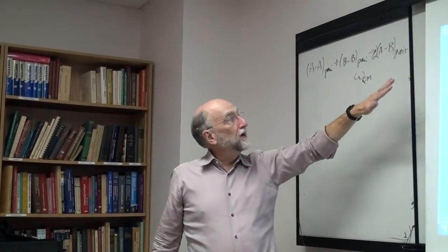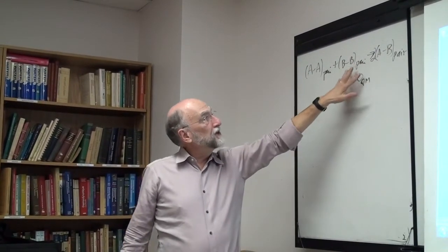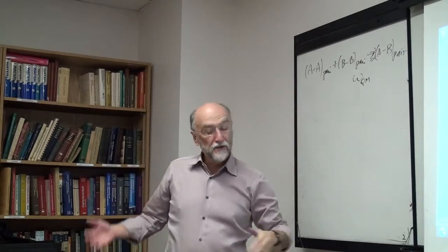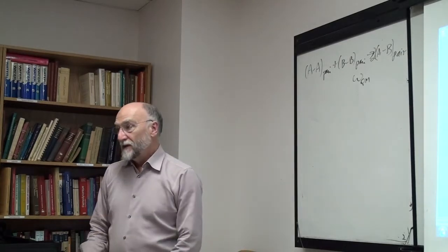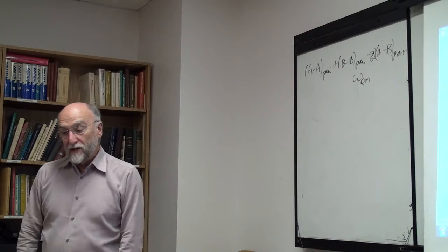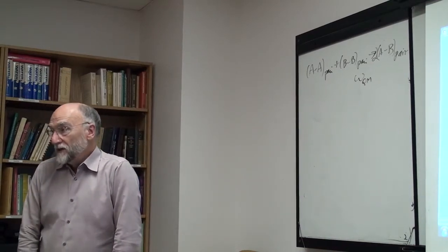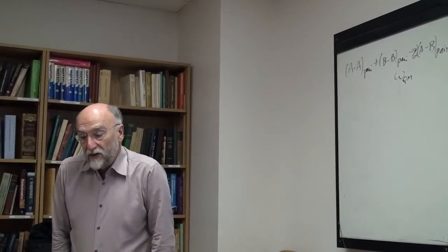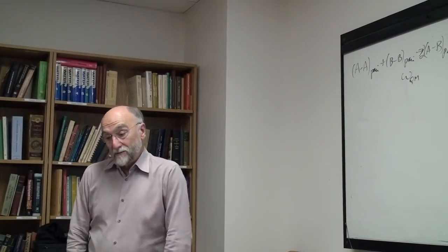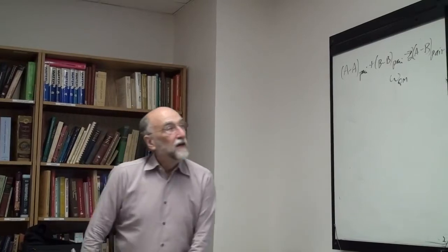In the Bragg-Williams model, you're fixing the entropy to be the ideal. You're not allowing the system to adjust its entropy. In the quasi-chemical model, the system will always try to find internally the internal structure which minimizes the total Gibbs energy. In the Bragg-Williams model, you're artificially not permitting it to change its entropy, to change its distribution.